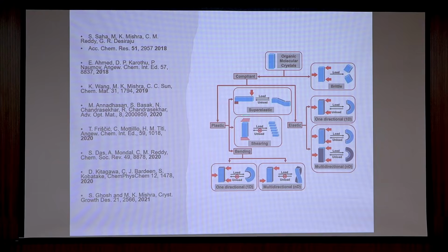that have so many different properties: plastic, elastic, super elastic, brittle. When does a crystal break, when can it be bent, when can it spring back. If the restoring forces are strong enough, it will become elastic. And all this on the basis of the interactions. And shortly after that, so many reviews appeared in top journals on this same topic. So once again, these are crystals whose properties are completely dependent on the fact that we are dealing with a complex system. Cannot happen in a simple system.